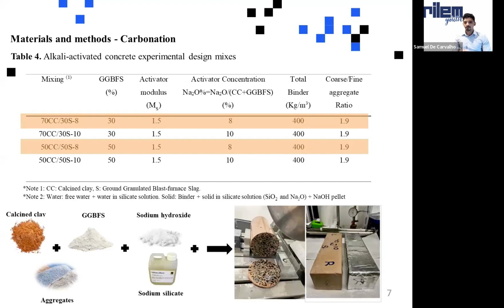So for the materials and methods for the carbonation experiments, that's my chapter 4. I'm showing you only four mix designs, but you have more in my thesis. These specific ones are the ones that had more compressive strength and performed better. Here you can see, 70CC means 70% of calcined clay, and 30S means 30% of slag, and 8 is the activator concentration, 8%.